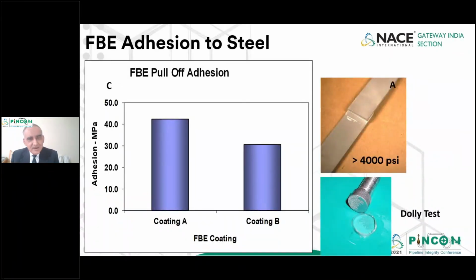Another third parameter is adhesion of the coating material. Because it's an epoxy, it bonds very strongly with the steel. It's called a structural adhesive. So there are two ways to test it. One is in the laboratory, where you see the brown picture A, which is the overlap shear strength. And if we do it that way, it will show me more than 4000 psi, which is a measure of structural